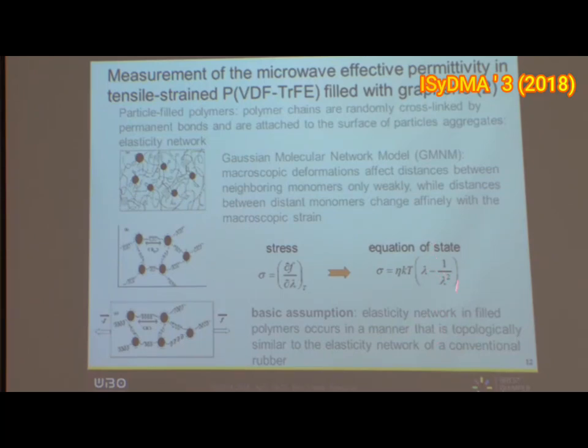This is the important term of what is called the Gaussian molecular network model, which depends on lambda, the elongation ratio, minus 1 over the square of lambda. Basically it states that when this law is experimentally checked, you get a system which is pretty similar to an elastomer with volume invariant in the deformation.